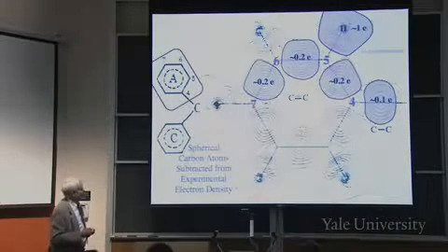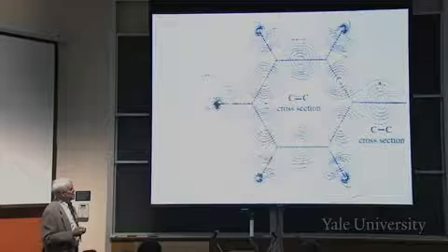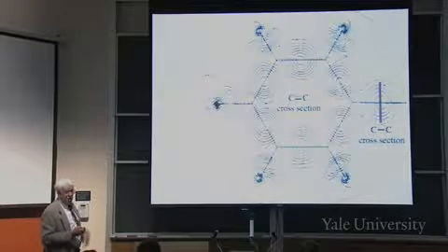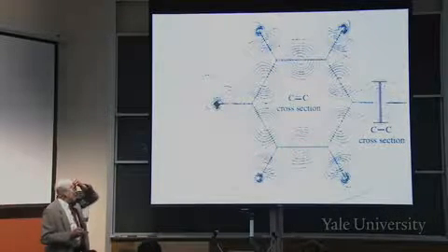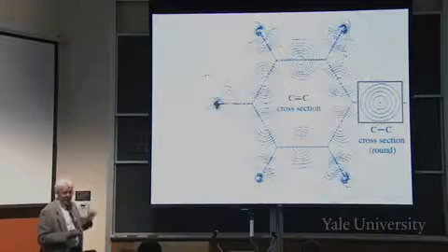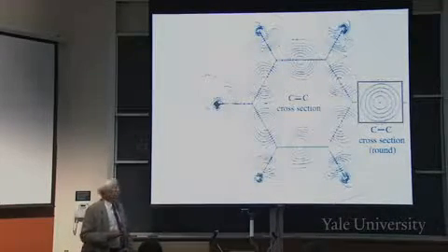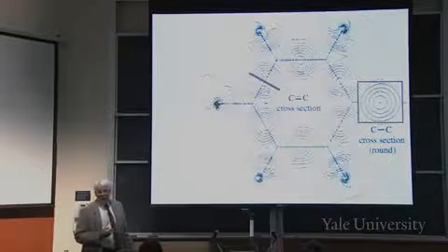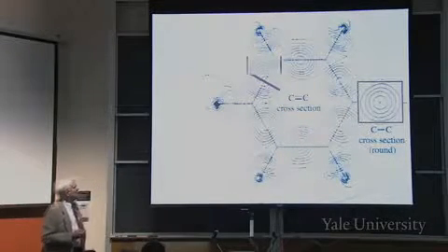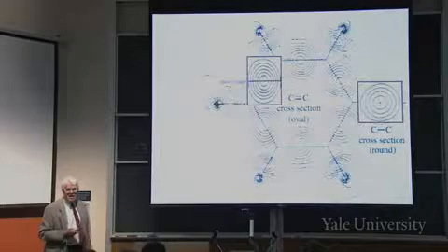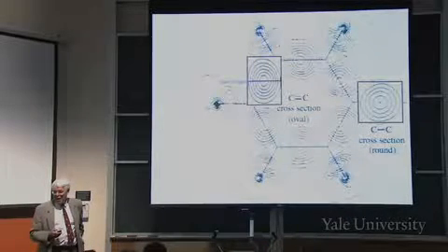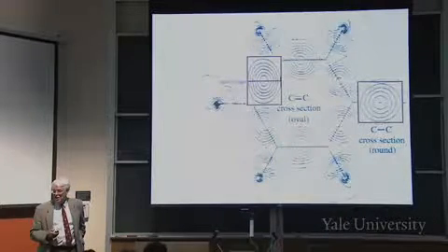Okay, so it's 0.2 electrons for those ones in the ring. Now let's slice it and turn it so we can see its cross-section. And it's round. No surprise there. But let's slice the ones in the ring and turn them. It's oval, not round. The bonds are not round. Why?